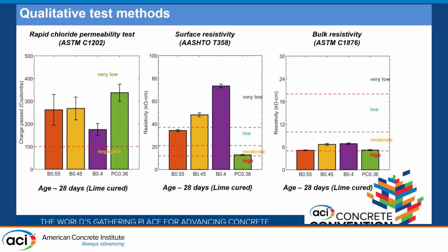Now let's move on to the results of the surface resistivity, where again you have a classification for concrete for the amount of chloride penetration based on the resistivity of the concrete. Here you can again see that for BCSA, it seems to fall in the range of low to very low chloride penetration. So as far as we compare the results of RCPT and surface resistivity, they seem to be in agreement for BCSA concrete specimens. But when we look into the results of the bulk resistivity, you see a contradiction. Here the resistivity has dropped and it seems to fall in the category of moderate chloride penetration.